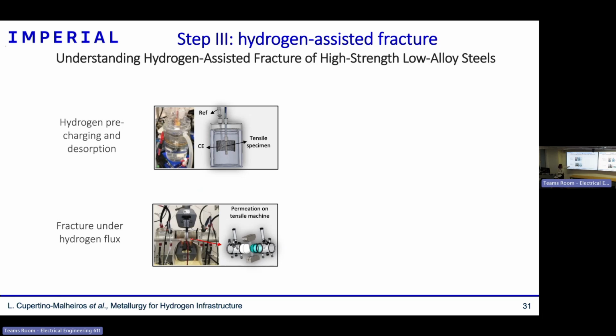Okay, the second test: I put the electrochemical permeation setup on a tensile testing machine. So in this test, we have a condition where, when we test the sample, when we pull the sample, there is a constant flux of hydrogen inside the sample, because here there is a charging cell and here a detection cell. And this condition simulates more or less a pipe, with hydrogen being charged on the inside and hydrogen diffusing out from the outside, the outer diameter of the pipe. So you have a gradient through the thickness and a flux of hydrogen through the pipe.